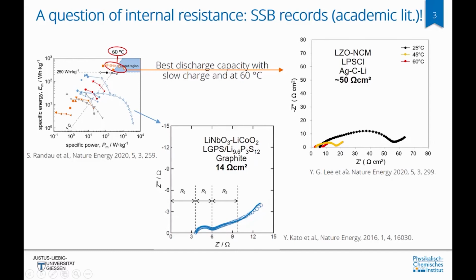And this is also evident from their publication in the Nyquist plot. They show at ambient temperature more than 50 ohm square centimeters as internal cell resistance, but as you go to higher temperatures, this drops significantly to below 30 ohm square centimeters in our competitive area range.